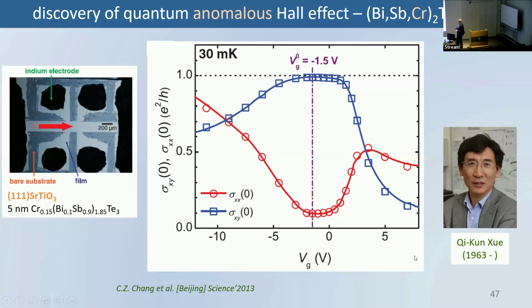And beautiful experiments done in Beijing show that indeed macroscopic samples now, they use a knife to produce this Hall bridge. At some concentration of carriers, which you regulate again by gate, you have very nice quantization, corresponding to 1, because now you have one chiral channel. And this resistance, the longitudinal resistance, tries to go to 0.